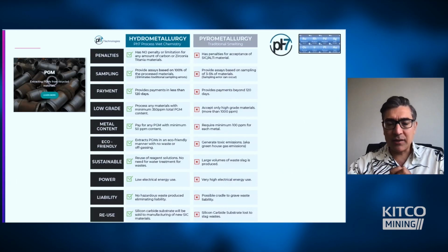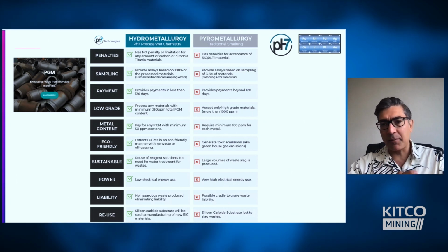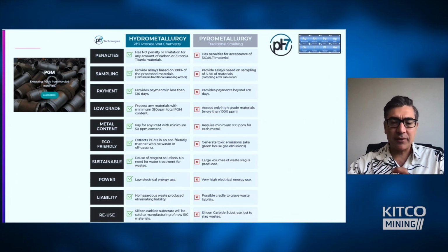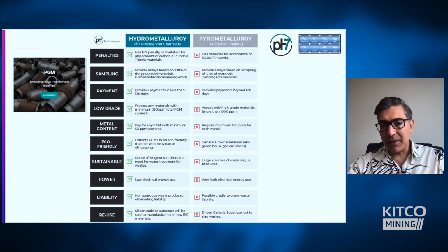Our process actually has a completely different approach. Instead of attacking the whole matrix and extracting the metals, we attack that 0.1 to 0.5% of the PGM, the valuable metals, and we extract them, dissolving them into the solution. And doing so, we're not relying on a matrix. Whatever matrix can be formed into a powder can be pumped through our reactors. We can extract it, so we don't have the limitations that we see in pyrometallurgical methods. So for example, if the melting temperature is really high, like silicon carbide or titanium, zirconia, titania, which is really hard to melt down in furnaces, we can easily process those types of materials.